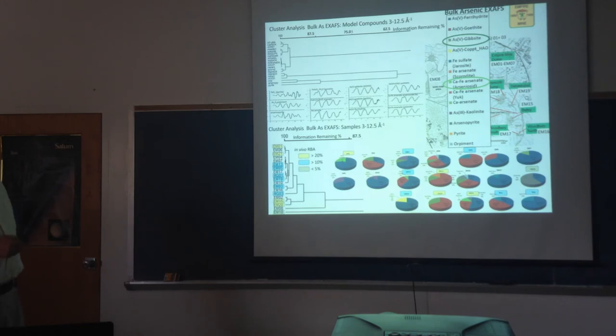So this is an area we're looking into in more detail, but this dark green is coming out of the EXAFS as aluminum gibbsite association. We need perhaps to get a better model compound for arsenic sorbed onto, say, aluminum silicates. And then finally, arsenopyrite is the least bioavailable.